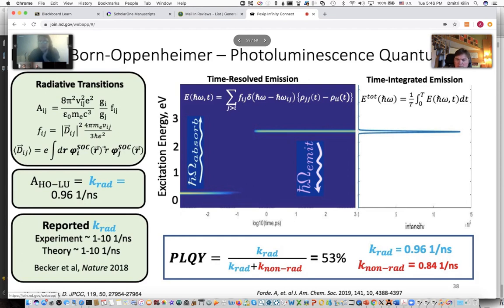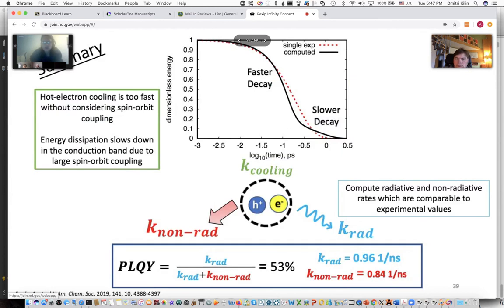The spectra being dominated by the photoluminescence signal. But then to characterize, this shows that its lowest energy transition is bright, but to get an idea of how efficient the transition is, we compute a theoretical photoluminescence quantum yield, which is this bottom equation, which essentially is just the rate of the radiative relaxation over the sum of the radiative and non-radiative. And due to the radiative and non-radiative essentially being on the same order of magnitude, we get an efficiency of 53% computed, which is fairly agreeable with experiment.